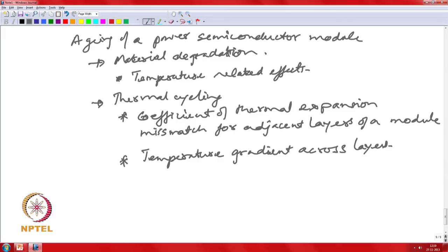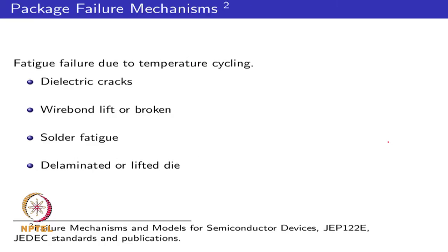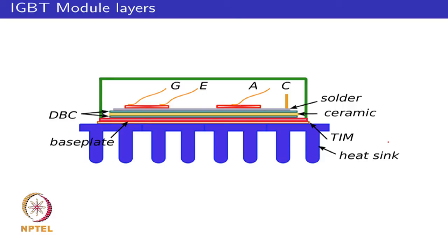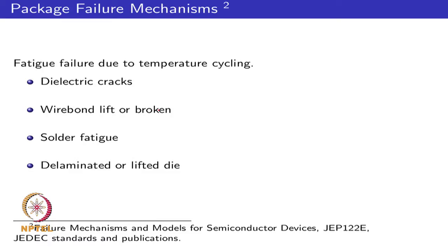For example, you might have silicon sitting on top of a ceramic layer. At 25 degrees centigrade room temperature, the silicon chip dimension might be 1 centimeter, and that might match your ceramic layer. But at 125 degrees centigrade, your silicon might expand from say 10 mm to 11 mm, while your ceramic might expand from 10 mm to 12 mm, which means the two structures now have a mismatch, and it is trying to buckle over or develop cracks at the corners. So you could have a variety of different concerns when operating such a power module.